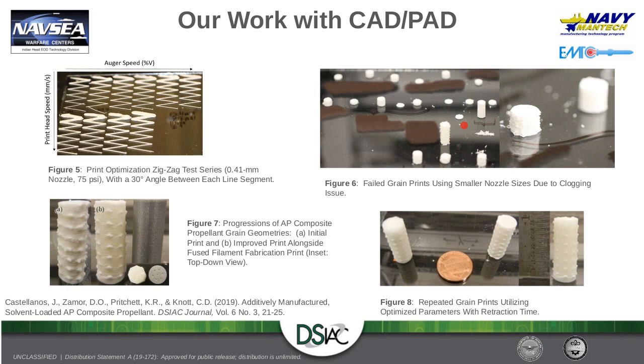Starting from how we would treat the material right after mixing and putting it into the syringe barrel, and then actually throughout the printing process, to make sure that we would have close to no agglomerates that could potentially clog the nozzle. However, despite our prudence in doing these things, we still ended up with a lot of clogging events with the finer nozzles, which caused us to need to go to the larger nozzle orifice diameter nozzles, which is 0.41. Once we moved up to the larger nozzles, we essentially went to almost zero clogging events, which allowed us to print several full grains without perforations.